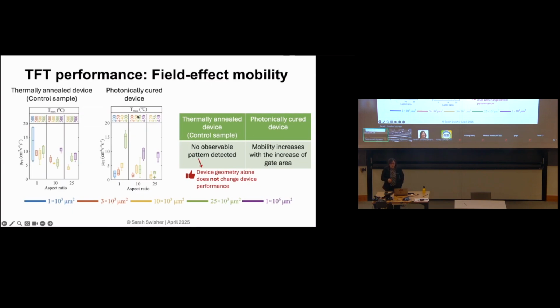Instead, what's causing this difference is that the mobility going up with the increase in gate area is essentially a function of this temperature going up, not of any parasitics that are inside the device.